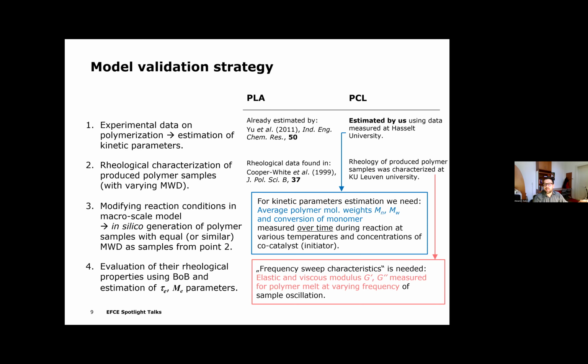So at Hasselt University, our colleagues carried out polymerization experiments from which we basically need average polymer molecular weights Mn and Mw, number and weight average, and conversion of monomer measured in time, hopefully at different temperatures and concentrations of co-catalyst, which is sometimes also called initiator by chemists.